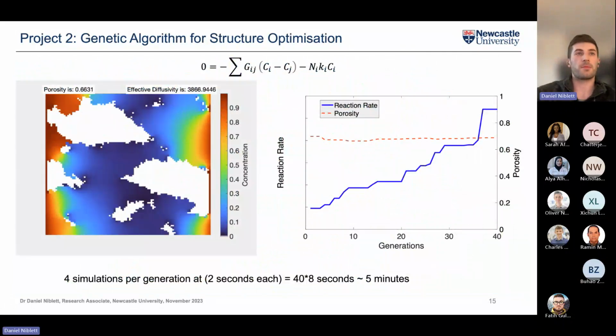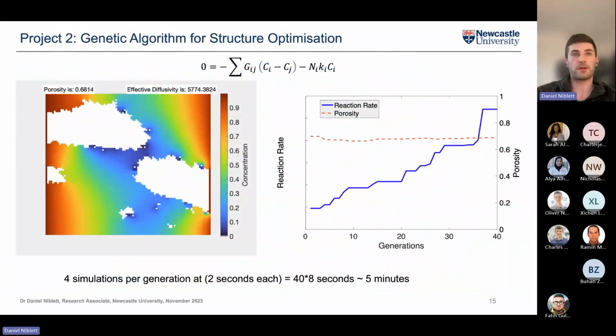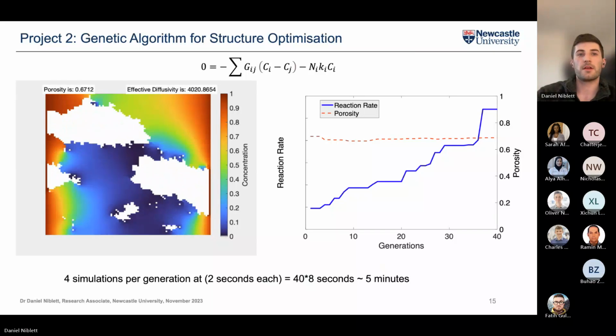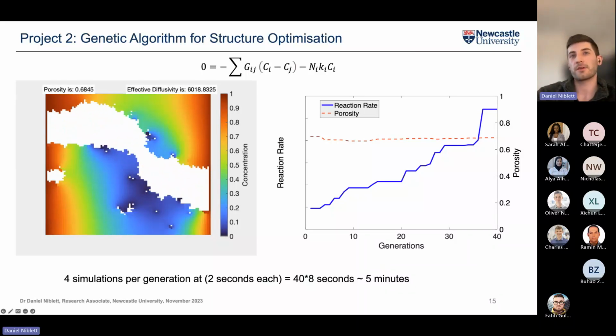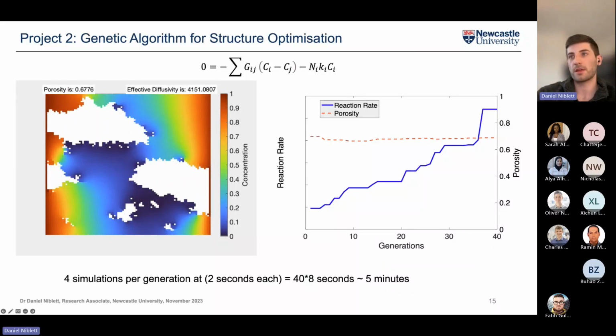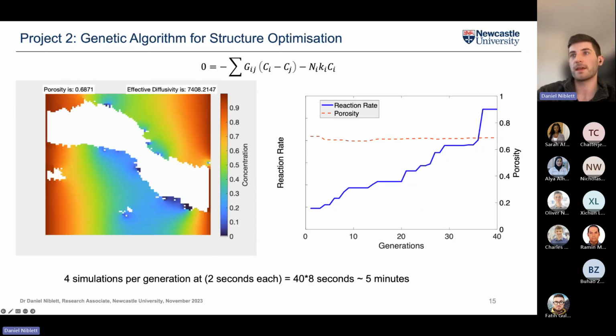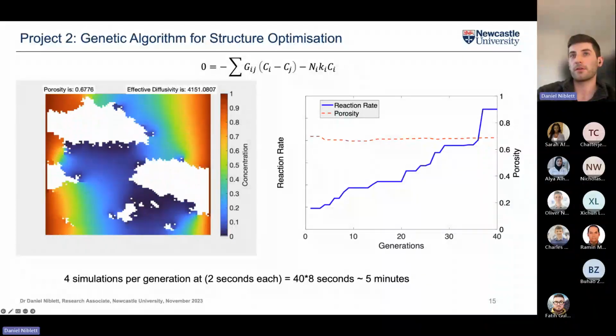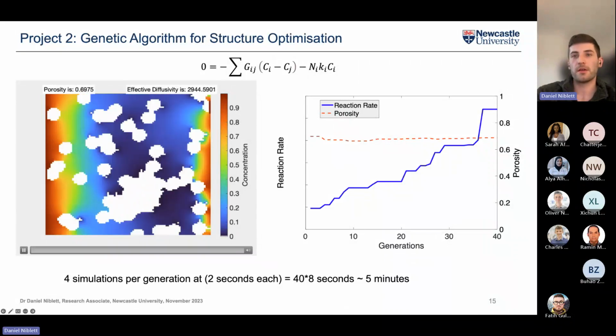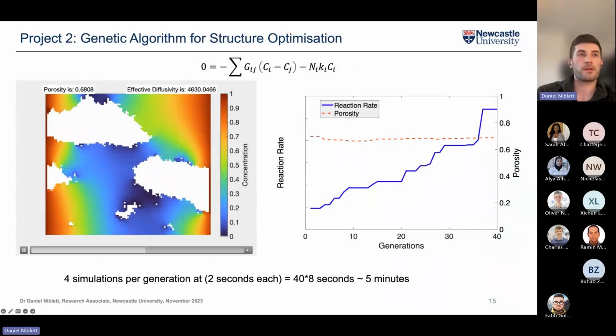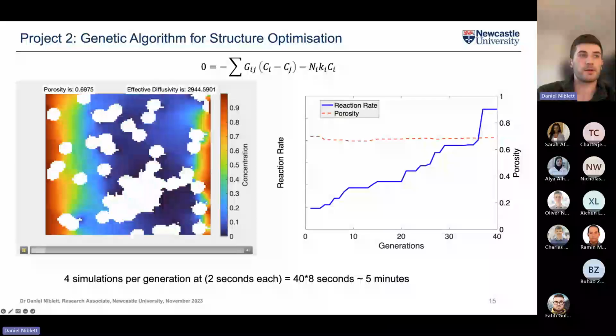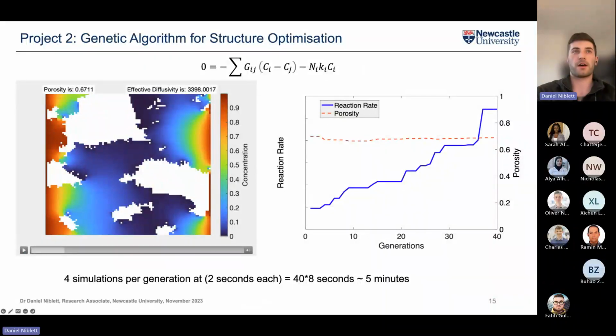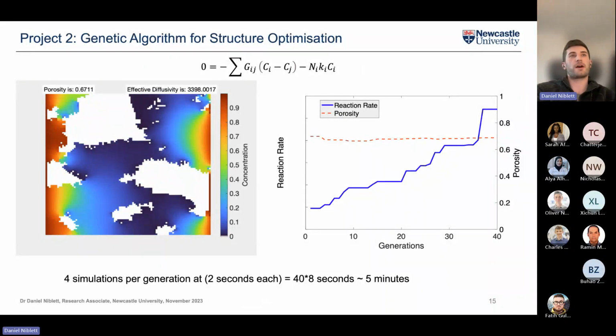And again, another type of the same simulation, but just different initial conditions. And you can see that, again, yes, it will optimize the reaction rate in blue whilst trying to maintain a very constant porosity across the generations. So this kind of simulation here took about 5 minutes, so it can run pretty fast if your simulation is fast.